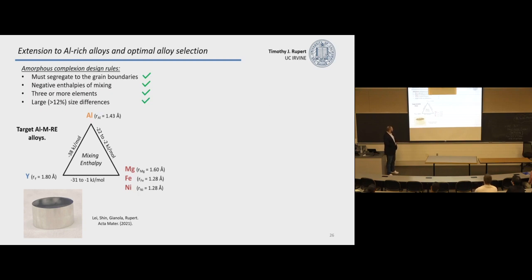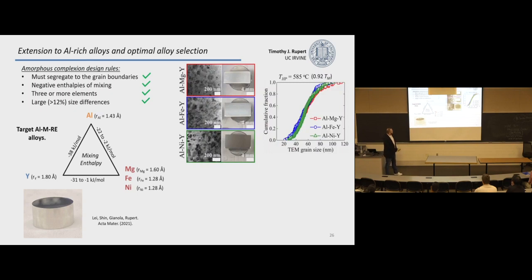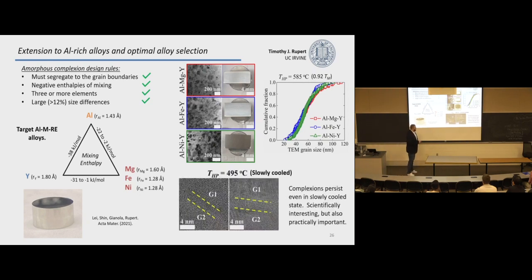But in this example, it's an aluminum-rich system where we're putting in some transition metals and magnesium, and then a rare earth metal, yttrium. We can make big bulk pieces of these nanocrystalline aluminum with grain sizes that are about 50 nanometers. So that's a good sign. But more importantly, what's really cool is, these are images of amorphous complexions in that sample. But in all the other things I've shown you till now, we heated it up to high temperature and then rapidly quenched it down.